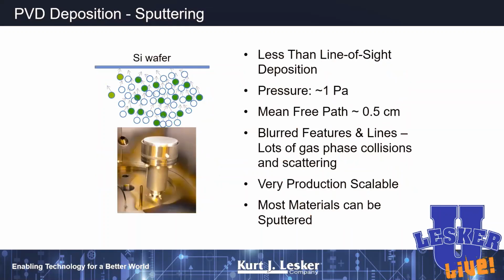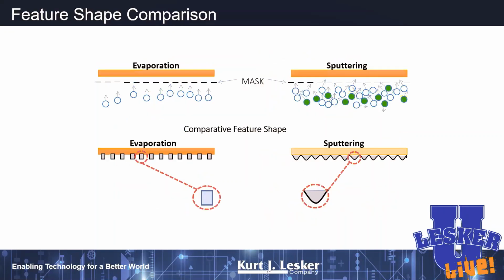If you look at sputtering, though, we have things coming off the target itself at strange angles, and then we've got all that extra process gas in the system where these atoms are going to collide and get even crazier angles coming off our sputter cathode. So if you think about trying to, let's say, evaporate through a mask, and we've got our incoming atoms coming in normal to the substrate, we can make some fairly crisp structures at the surface of our substrate. Whereas with sputtering, where we've got these atoms coming in at all kinds of rakish angles, we don't get very good resolution with respect to our mask, and so we get some pretty fuzzy looking depositions.